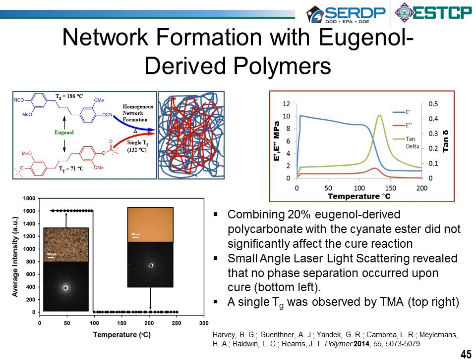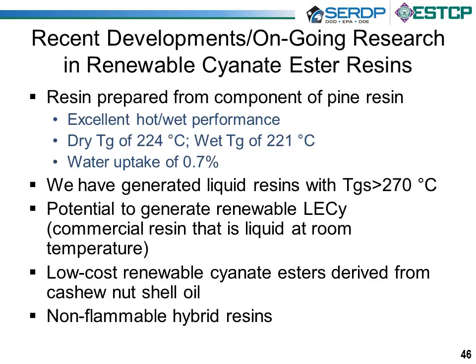So I'll just really quickly summarize some of the recent developments that I'm not going over in this brief, but that you'll hopefully be hearing about in the literature very soon. So we've prepared a resin from a significant component of pine resin that has outstanding hot-wet performance, has a dry TG of 224 degrees C, but a wet TG that only drops by 3 degrees C to 221 degrees C, and it has one of the lowest water uptakes we've ever seen for a cyanate ester resin of 0.7%. We've also generated liquid resins on 100-gram scales that have a glass transition temperature of greater than 270 degrees C.